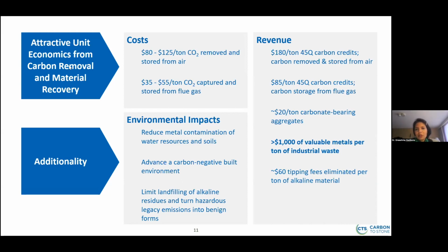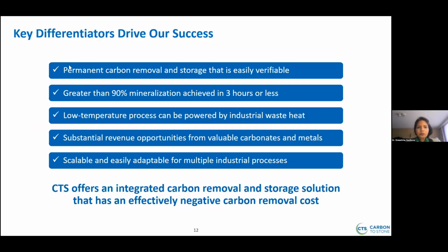So the first is being able to achieve a revenue of about $180 per ton based on the 45Q tax credits. There are a lot of valuable metals actually present in some of these slags. And so if you're able to recover those, the value can be upwards of $1,000 per ton of industrial waste that's processed. And we eliminate the tipping fees altogether for disposing some of these alkaline residues. There's also a revenue stream associated with using the carbonates, and we anticipate that's somewhere in the range of $15 to $20 per ton of carbonate-bearing aggregates. So there is actually potential to be profitable while doing good for the environment here.